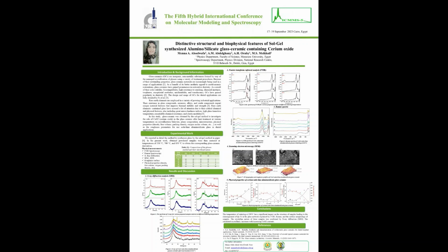Finally, the physical properties of cerium soda lime aluminosilicate glass ceramic in figure 8. Glass density is related to molecular weights. In our investigation, CeO2 rose at the sacrifice of Na2O and CaO, resulting in higher density.